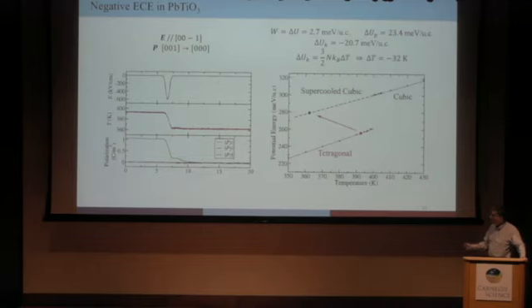So a half-cycle pulse. The temperature is constant, and then it drops significantly right around the time that the electric field is being applied, and the polarization goes to zero. So we have driven the system from the tetragonal phase to the cubic phase, and it's significantly lower temperature. And it's supercooled in the sense that at this temperature, it really would prefer to be in the tetragonal phase, but it doesn't know that. It takes time for nucleation and growth to reassert itself.